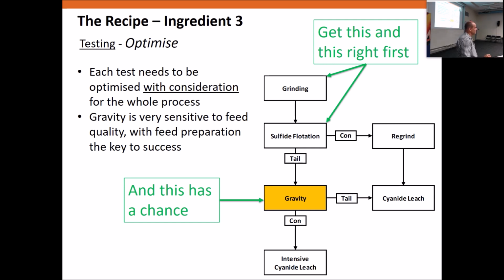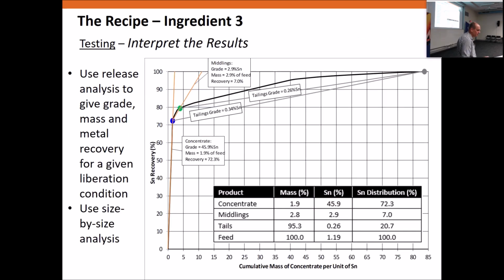And no one seems to get too excited when you talk about optimising flotation tests, where everything from the source of the water to the grinding media and the chemical conditions are considered by a competent lab. But it's quite common to see a bad gravity test result taken as gospel, even though the poor thing was fed with a lot of rubbish. So the last part of ingredient 3, testing, is interpreting the results, and we've already shown what can happen if the laboratory or the design engineers don't recognise that 0.03% mass recovery to a concentrate is unlikely to give you the same recovery as a 6 or 7% mass recovery does.